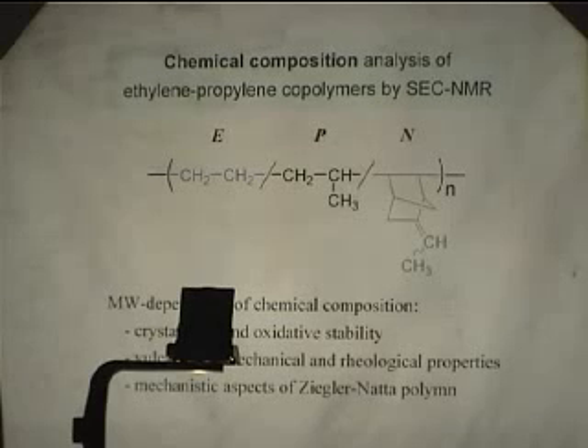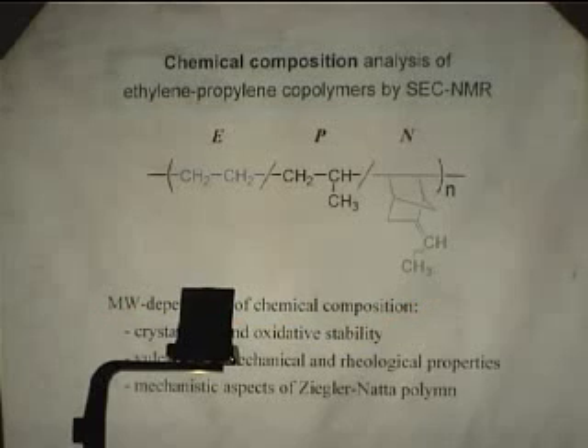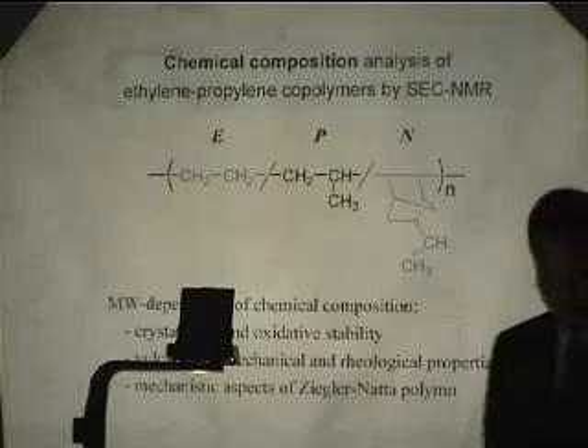Since the properties of this material depend on both molecular weight distribution and chemical composition, the analysis of the molecular weight dependence of chemical composition is very important for understanding the structure-property relationship of this polymer. For example, crystallinity, oxidative stability, vulcanization, and mechanical and rheological properties of EPDM are very dependent on chemical composition and molecular weight distribution. So the analysis is very important for the industry. The information on chemical composition against molecular weight is also useful for understanding the polymerization mechanism, in this case, Ziegler-Natta polymerization.